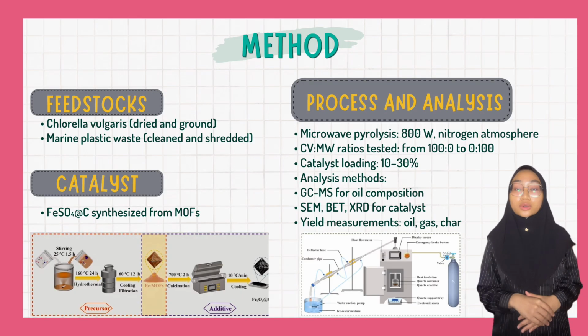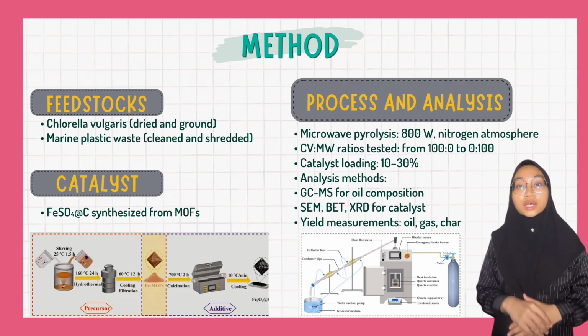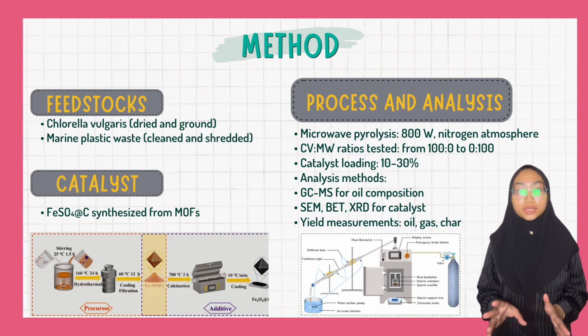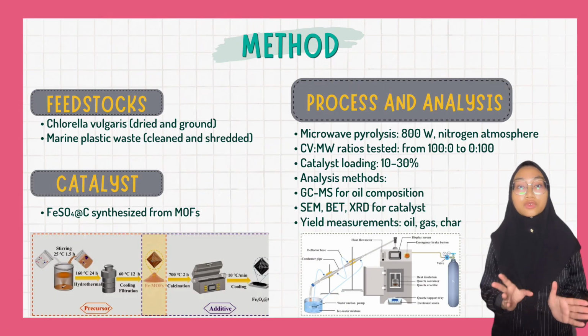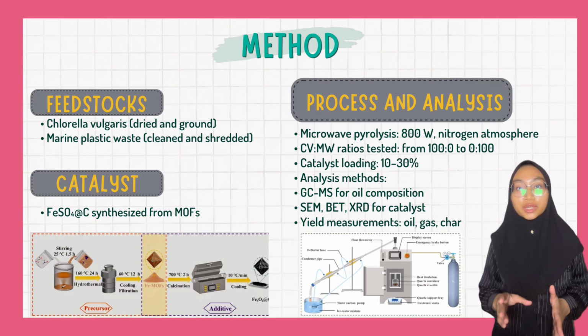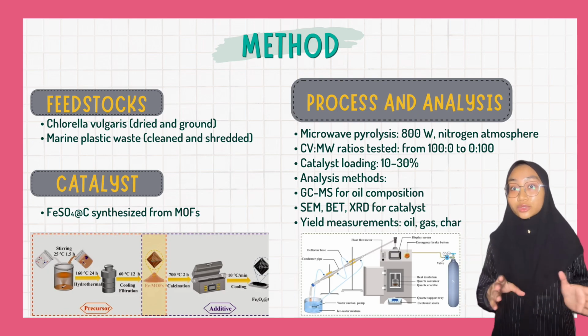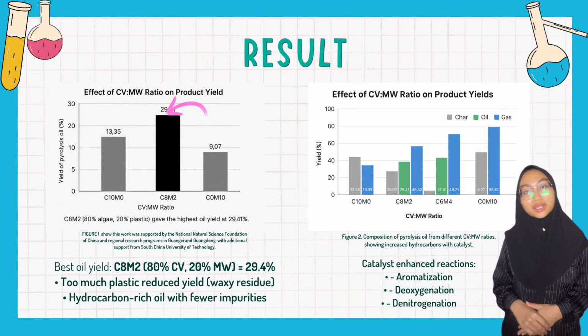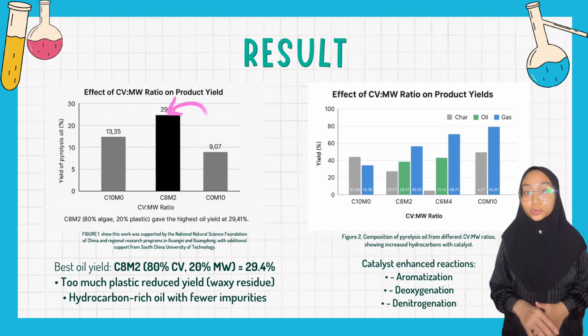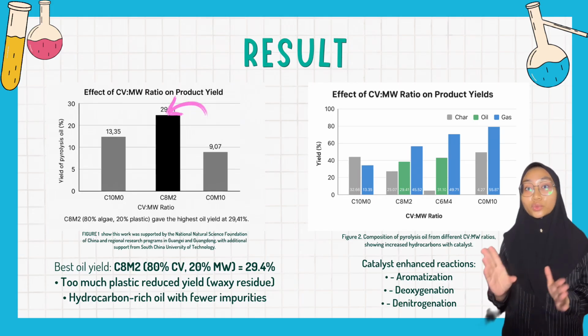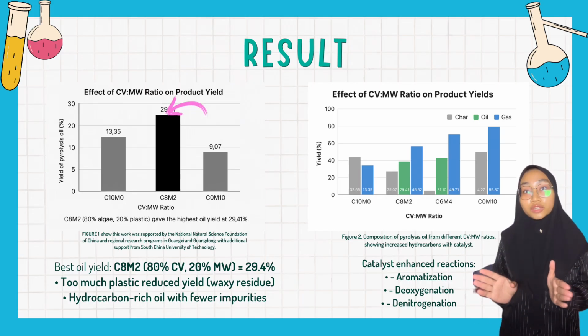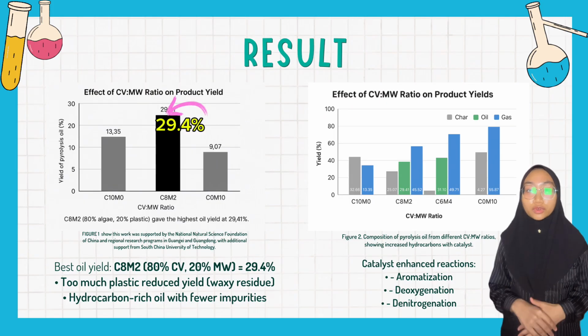Our ferrum oxide or C catalyst was derived from MOF because of their high surface area and tunable properties, making them excellent for catalytic reactions. Our best result came from the C8M2 ratio, which is 80% algae and 20% plastic. This ratio gave the highest oil yield at 29.4%.